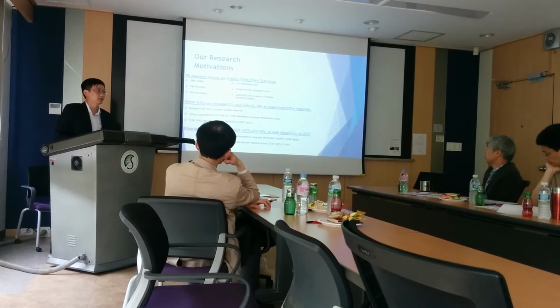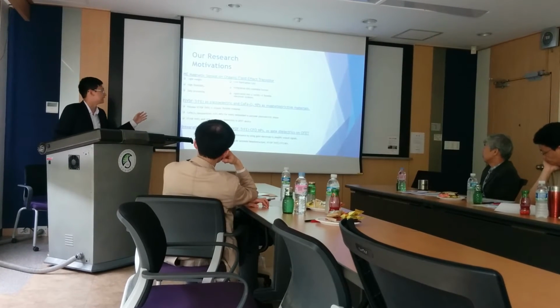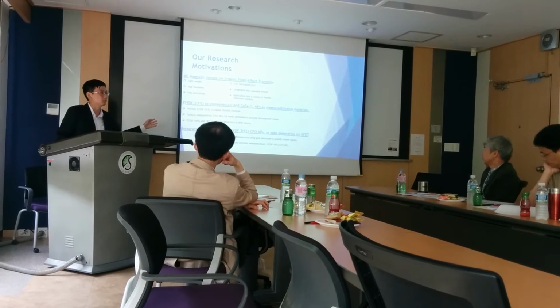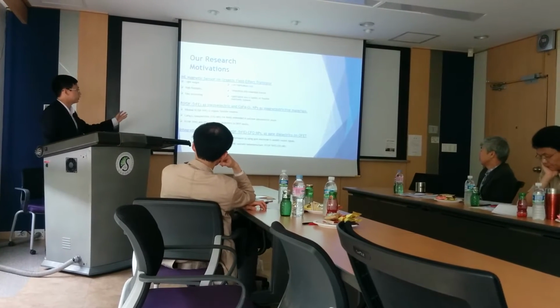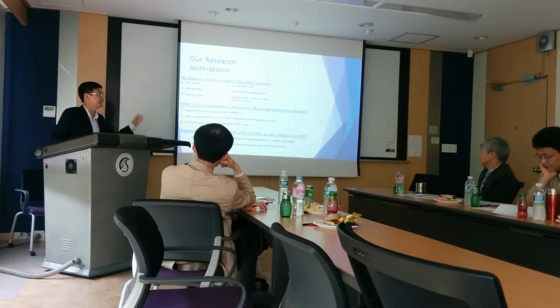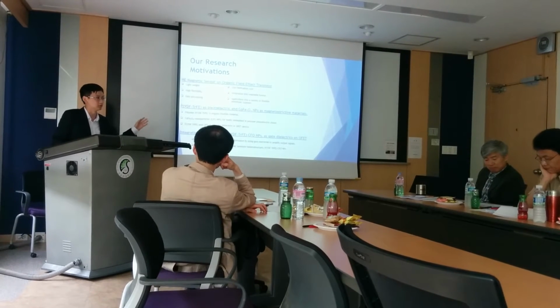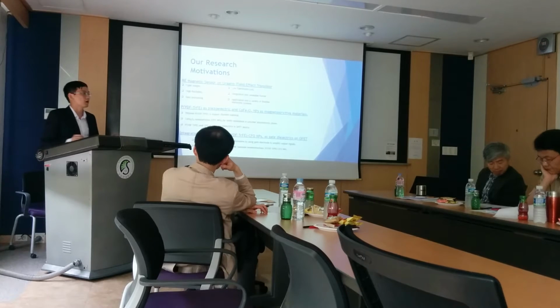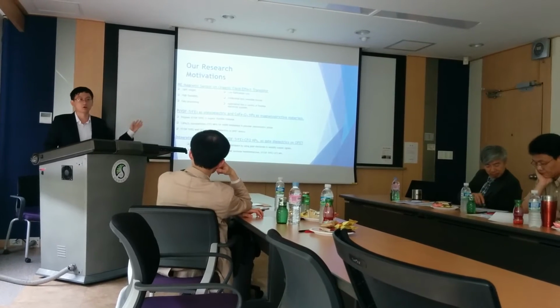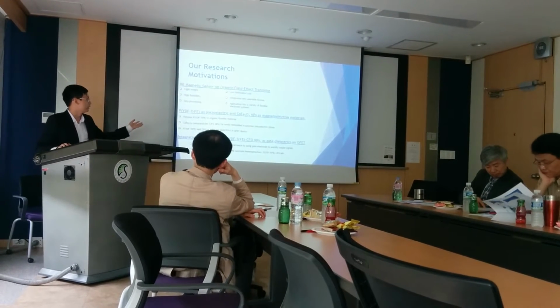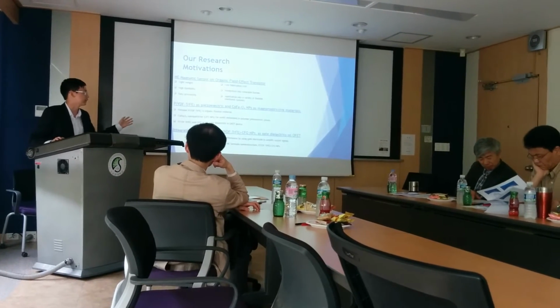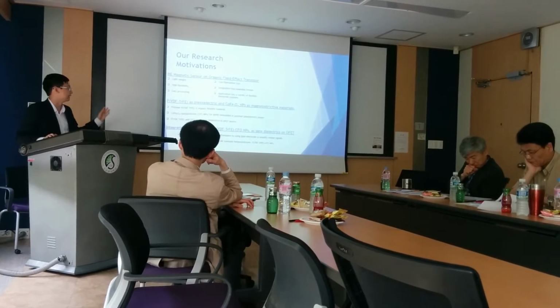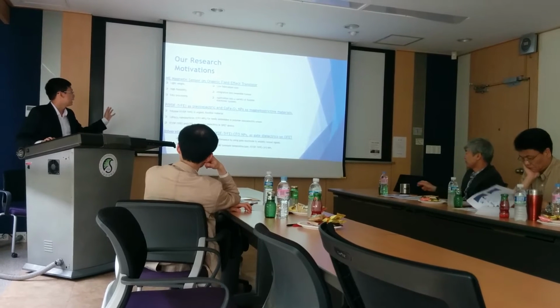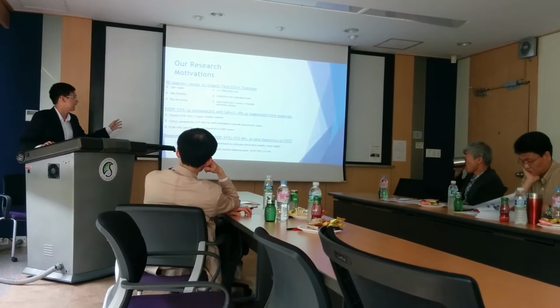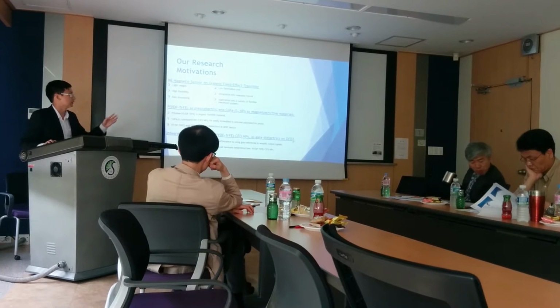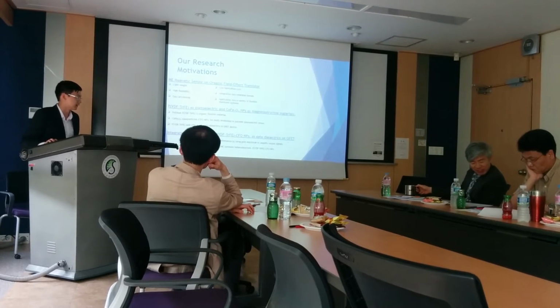Polymer PVDF-TrFE is chosen because it has the advantage of being an organic flexible material. Cobalt ferrite nanoparticle is chosen because it is easily embedded into the polymer piezoelectric phase. If we combine the PVDF-TrFE and cobalt ferrite CFO, we will have the magnetoelectric composite, and we will integrate the ME composite as the gate dielectric on the organic field effect transistor.